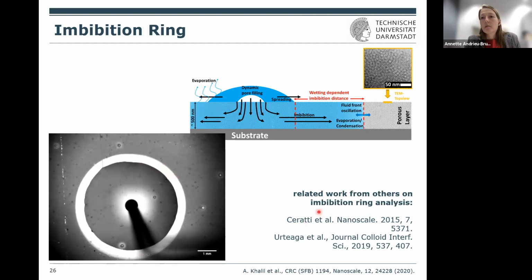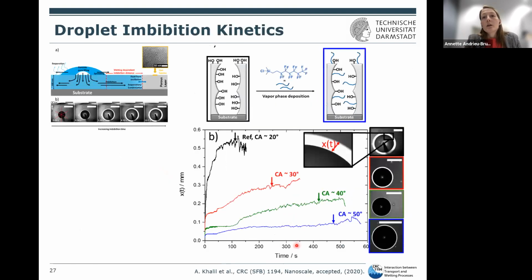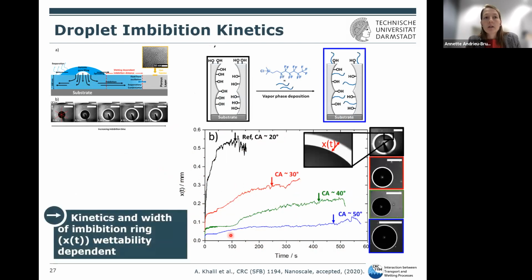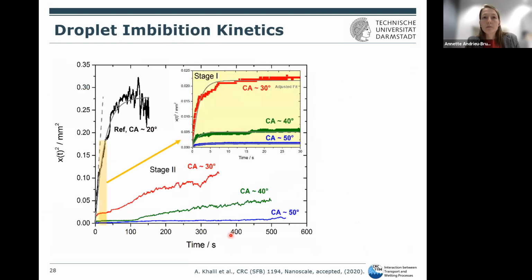And this was motivated by a work from an Argentinian group as well, who did this for different mesoporous structures. Yeah, this is the Argentinian group, and this is the group from France, actually. What you then get is just plotting the x(t), so the width of the imbibition ring against the time. So what you saw in the video, basically 4 samples with different contact angle. And then you see these curves that are very different in their initial phase, and then differently here in what we call the second stage as well. So the kinetics of fluid imbibition obviously depend on the wettability of these pores.